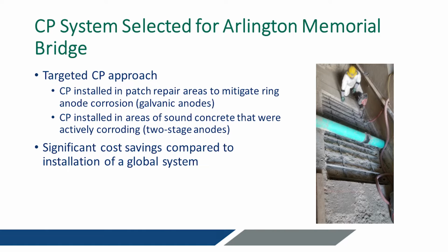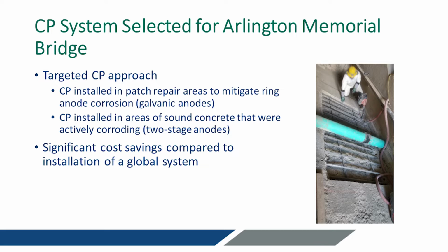And so we're just installing the anodes in areas around patches to prevent any kind of ring anode halo effect issues. And then in areas where there is active corrosion or a high risk for corrosion, we'll install it there to prevent and stop that. So it's a lot more cost savings than, say, a typical impressed current system, where you might install it on the whole surface area, even areas that may not necessarily need it at that time. By doing a targeted approach, where we're really just targeting the areas that are potentially at risk for corrosion, we can save a lot of money for the owner and apply it just where it's needed.